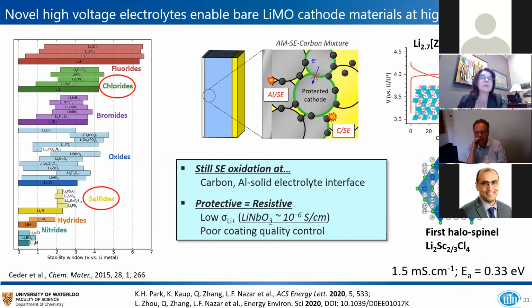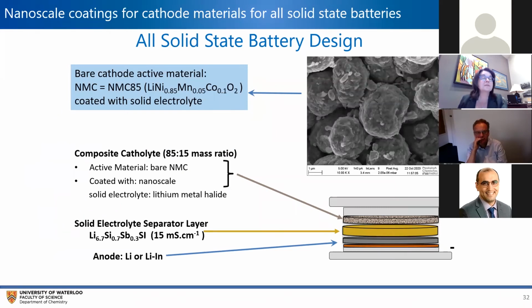So I'll talk a little bit now about how we build our batteries, just to end off on some practical things. And this is where the nanoscale becomes important. So in the diagram on the upper right here, what you see are particles of this state-of-the-art lithium nickel manganese cobalt oxide. These are called NMC. This is a high nickel content material, which means it can be used at a fairly high potential. And we have literally coated the material with one of these halides. And it's a little hard to see because I don't have a cross section, but effectively this is on the order of 100 nanometers of halide coating on the material.